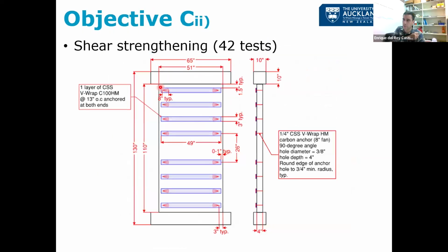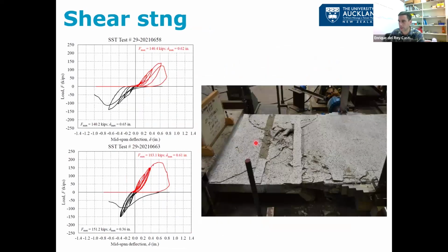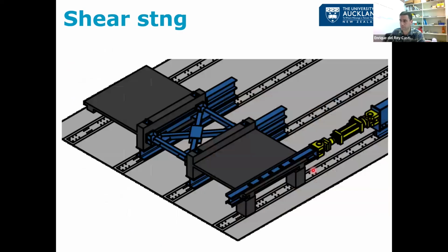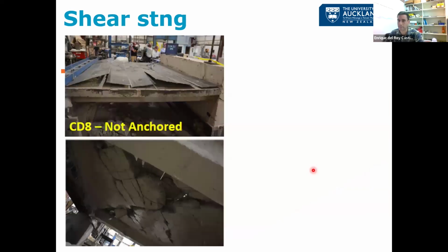Similar with shear strengthening, we have another 42 tests. The FRP is crossing the crack, so we have the cracks going like that. We can see that in the test. The cracks go like that, and we have the FRP crossing those cracks. This is more challenging because it's shear failure. So we want to transform an inherently brittle failure to a more ductile failure. So it's proving to be more challenging. But some tests at Virginia Tech that I was slightly involved with have demonstrated that we can do this. We can increase the shear strength and we can shift the failure to another part.